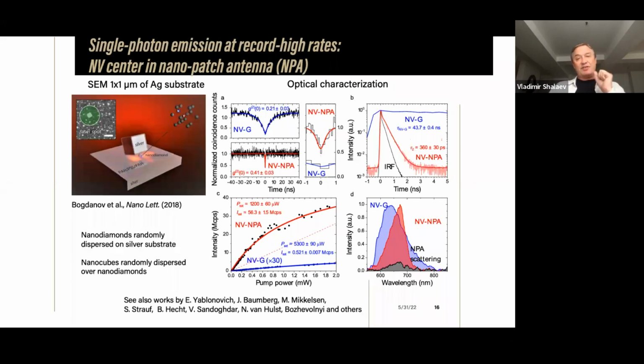In this case, we simply took epitaxial silver of really high quality and randomly distributed nanodiamonds of small sizes, like 25 nanometers, some of which have this nitrogen vacancy and could work as single-photon emitters. Then we randomly distributed the silver cubes. Just by chance, in some cases, a single cube would find itself on top of a nanodiamond, and that could work as this nanopatch antenna I'm talking about. To prove that we're dealing with single photon sources, you do the typical G2 correlation function measurement. And if it goes below 0.5, then you could say that this is a decent single photon emitter.